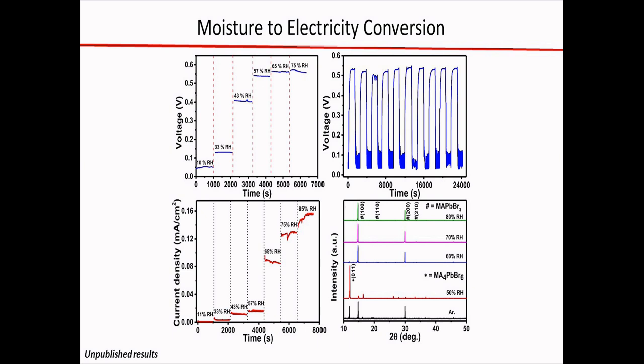We also measured the current. The current is also maximum around 65% RH, because this is the point where we have more ions that are generated, and the more ions result in ionic conductivity in this material.